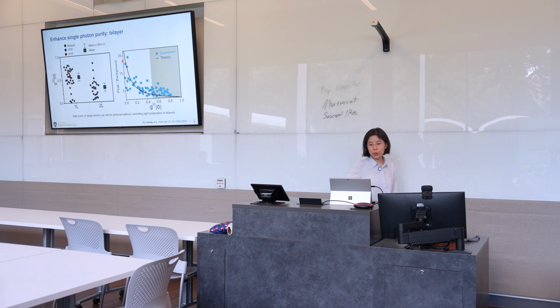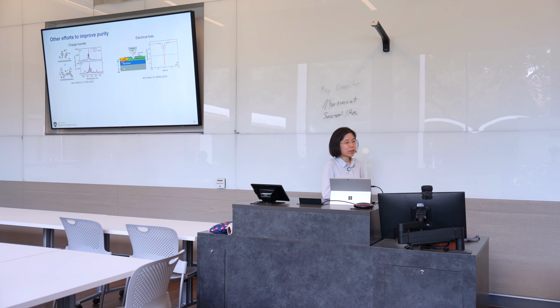So I also need to mention there have been other efforts to improve single photon purity. For example, people try to use the charge transfer molecule to suppress the classical background. You can see in this work, they use this type of molecule and put it on top of tungsten diselenide. The sharp peaks from the emission will show up, and these are actually single photon emitters. But without these molecules, they cannot see single photon emitters. In addition, you can use electrical bias to deplete some charges from tungsten diselenide.